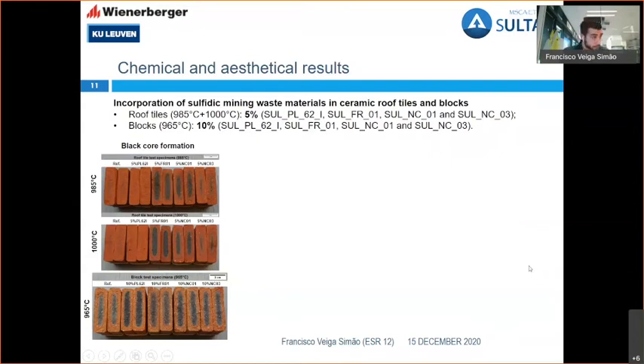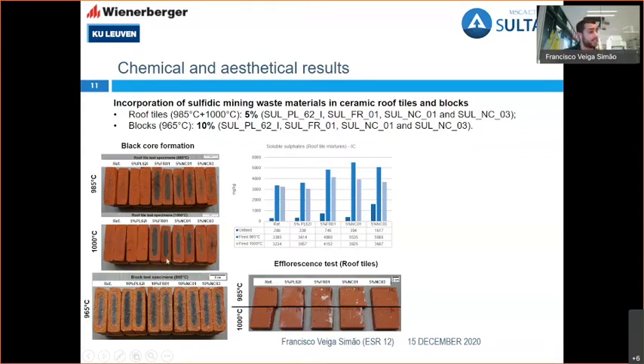On these fired test pieces, you can see how the high content of carbon and sulfur influences the black core formation on the mentioned mining waste tailings. Of course, this carbon and sulfur are oxidized, and especially the sulfur oxides create a reducing atmosphere that during firing creates this black core formation. This black core formation, especially in roof tiles, is quite a point to make reference to, as it also reduces the durability in the frost-thaw cycles, so the frost and defrost cycles. So that's why, in the reference, you see that Plombières is really close to the reference visually and also chemically, as you will see now on the soluble sulfates and efflorescence tests on these two products.